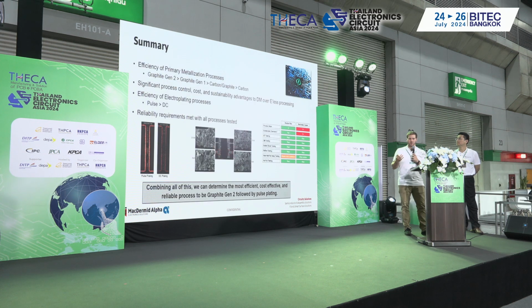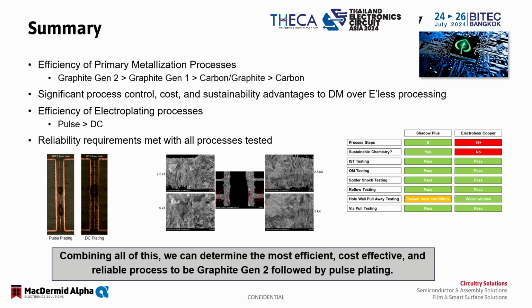So, in summary, when we look at our efficiency of the primary metallization, we saw that our graphite Gen 2 performed better than our graphite Gen 1, which performed better than our carbon and graphite mixture, which performed better than our carbon. You can see a significant process control, lower cost, and higher sustainability using DM over electroless copper. So we believe that's the way we should be going forward.